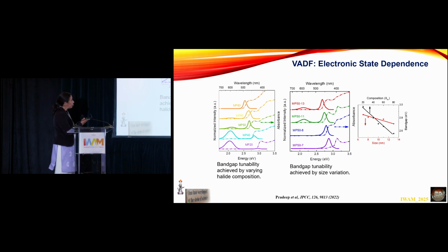So we have samples which are going from 20% chlorine to all the bromine to 80% bromine. And we took something around 50%, and we said, okay, I'm going to change the band gap by changing the size from 7 nanometers all the way up to 13 nanometers. And you can see that the band gaps are varying in a similar region. So now I wanted to see what is the effect on VADF.